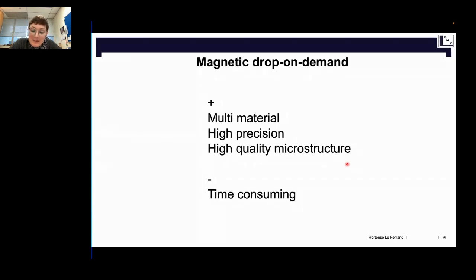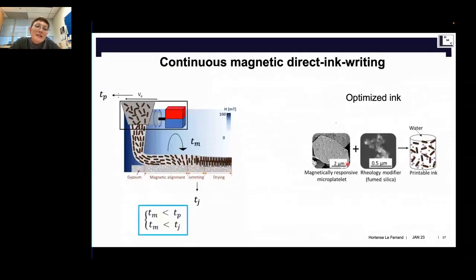So this motivated this second technique, which is continuous magnetic direct writing. Here the principle is to make an ink that we extrude directly, and while we extrude it, we align the platelets that are inside this ink, and at the same time we print on a slightly porous substrate that will dry and fix the microplatelets in their orientation.